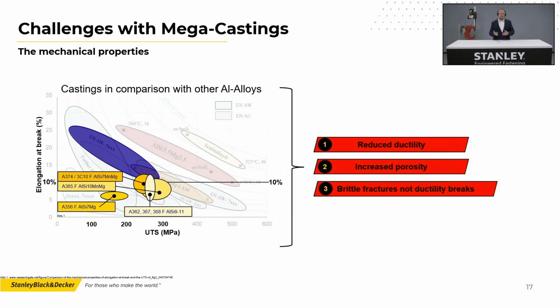But what they all have in common, especially when they are not heat treated, is that they are brittle. They have a reduced ductility based on elongation at break. I use elongation at break as an indicator to say something about the ductility of the part or the material. We know that there are more indicators that say something about the complete ductility of a part or a material, but I use elongation at break in this case, and going further, we'll keep on using elongation at break as that defining ductility value.